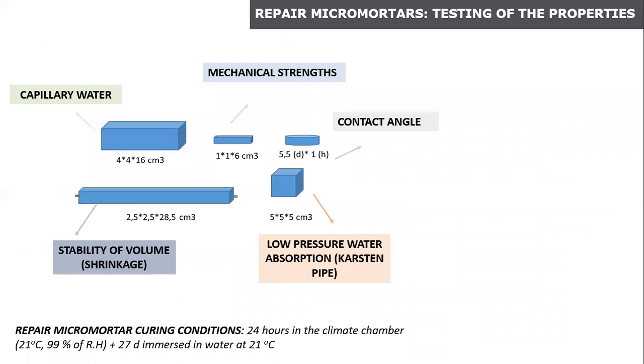Well, with these dosifications, we have prepared several types of mortars in order to test different properties. So we have analyzed the mechanical strengths, we have analyzed the stability of volume, and we have measured the hydric performance through the analysis of the capillary water, the low pressure water absorption, and finally the contact angle.